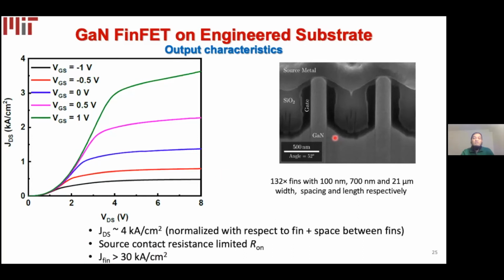So although currently the normalized current density over the active area is about 4 kiloamps per centimeter squared, in future we can make the fin density higher and even achieve a higher current rating from these devices. So this current density is showing a potential for further scaling of the current rating of these devices.